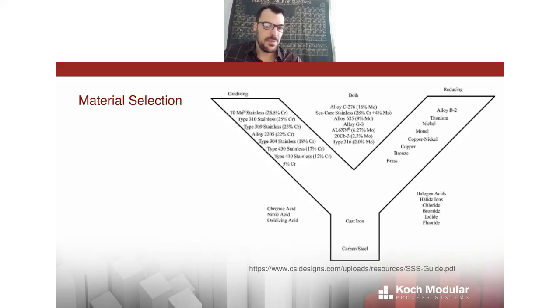On the left side, by contrast, we have nitric acid, chromic acid. These acids are oxidizing acids because, for example, nitric acid, after it gives a proton to the metal as a corrosion agent, the residual NO3 anion can do further chemistry. It can give an oxygen up as well, which would then lead it to evolve NO2 gas. So because the anion also participates in corrosion, it is an oxidizing acid. In the case of oxidizing acids, you generally want higher and higher chromium levels to resist the corrosion rate.